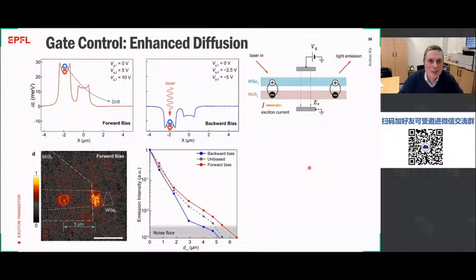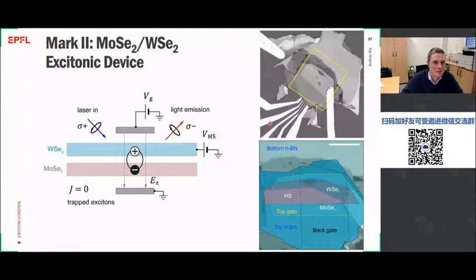But now at this point, we thought, okay, this is all very nice, but we would also like to somehow introduce this polarization and the Valley physics and the Valleytronics into these devices. And we couldn't do that using this combination of materials because this transition was between the gamma and the K point. And in the gamma point, we cannot have Valley polarization. So the light which was coming out of the device couldn't be polarized. And to go around this problem, we switched molybdenum disulfide for molybdenum diselenide. So we made the next improvement in devices.